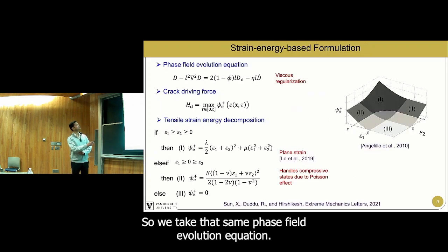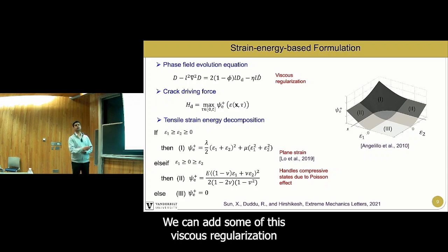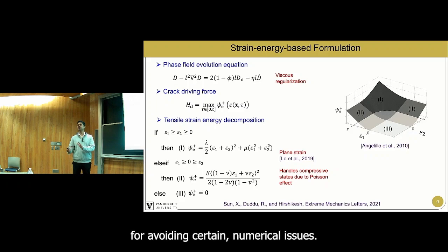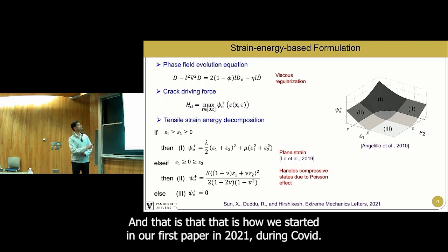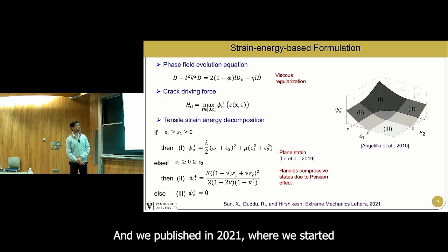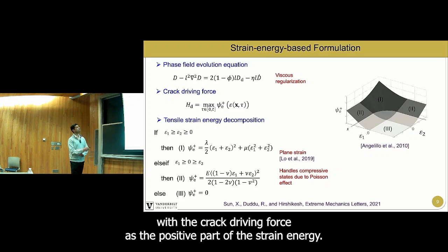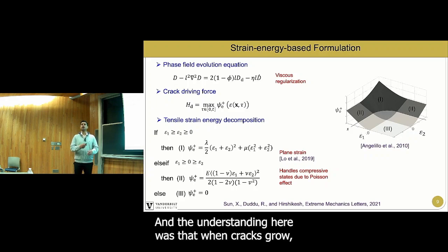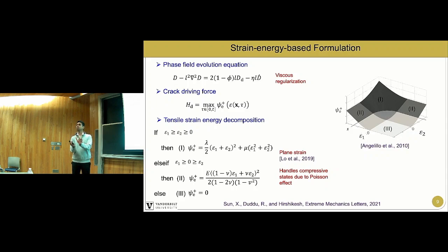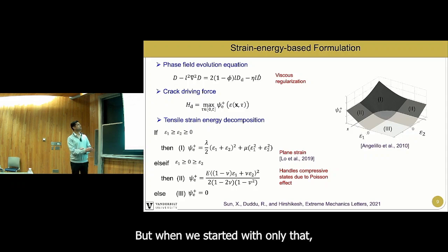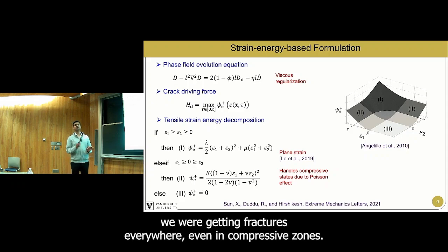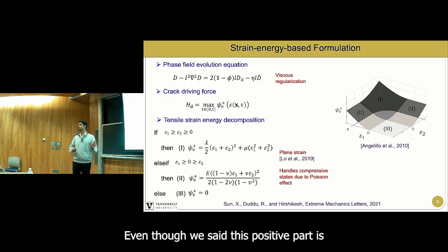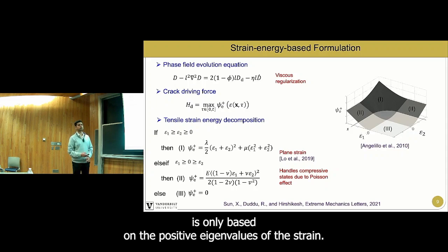So we take that same phase field evolution equation, and we can add some viscous regularization for avoiding certain numerical issues. And that is how we started in our first paper, which we published in 2021 during COVID, where we started with the crack driving force as the positive part of the strain energy. And the understanding here was that when cracks grow, they grow in tension, not in compression, right? Brittle fracture. But when we started with only that, we were getting fractures everywhere, even in compressive zones, even though we said this positive part is only based on the positive eigenvalues of the strain.